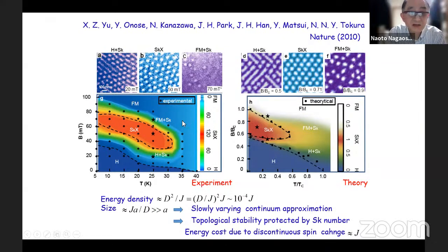But very interestingly, here is some point where you observe the isolated skyrmion is stable also in the simulations. So namely, you don't need a lattice structure to stabilize the skyrmion. The single skyrmion can be stable as a single particle, right? Another message here is the energy scale of temperature and magnetic field are quite different, because this is of the order of 10 or 30 Kelvin, but this is a millitesla, right? So this magnetic field energy is much, much smaller than the temperature scale. This difference is actually quite important for the physics of the skyrmion because there are two energy scales.